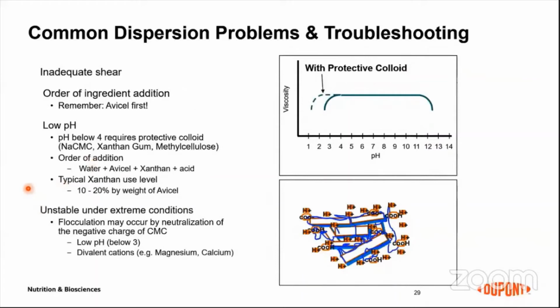But if there are low pH ingredients in your formulation, because colloidal MCC has a stable pH range from pH 4 to pH 11, sometimes if you have a much lower pH, you need to think about a protective colloid like CMC or xanthan, even methylcellulose. So try to add and disperse Avicel firstly. Then any low pH ingredients or acid can be added at the final step. And you can add 10 to 20% by weight of Avicel protective colloid for the low pH formulation, right?